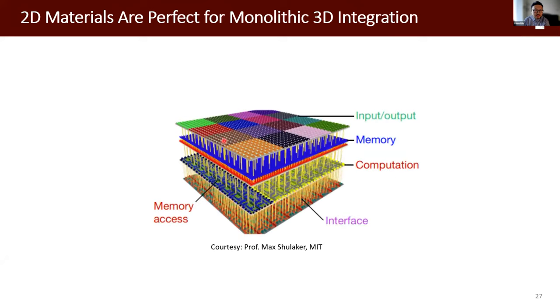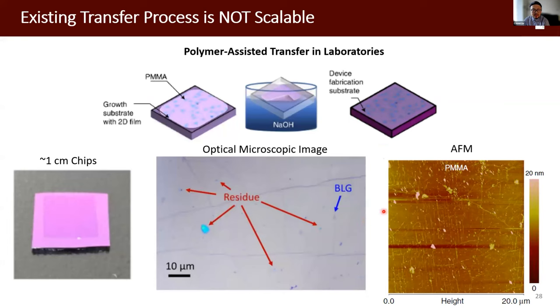So our vision is to integrate 3D monolithically integrated computing and sensing systems, integrate different functionalities, and this is not possible without the easy 3D transfer approach. But in laboratory right now, the transfer is mainly based on a polymer-assisted transfer. So we spin coat a polymer onto the substrate as the supporting layer. And with some chemistry, we can peel off the 2D material polymer stack from the substrate, and then we can transfer onto the targeted devices. So this process is manual and less controllable.